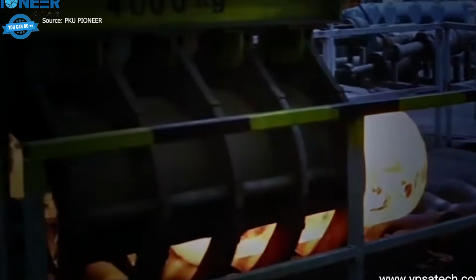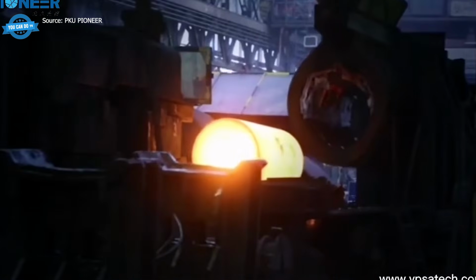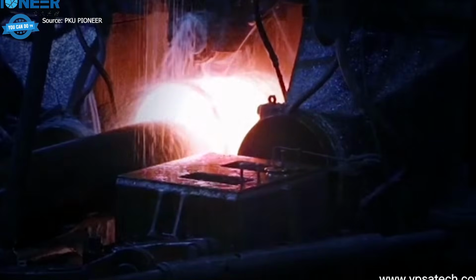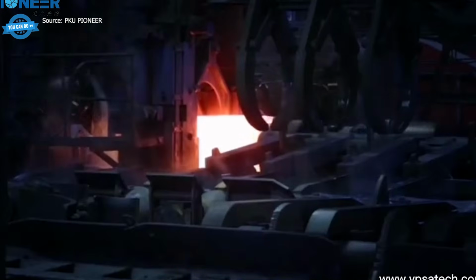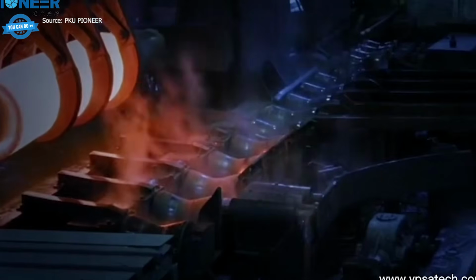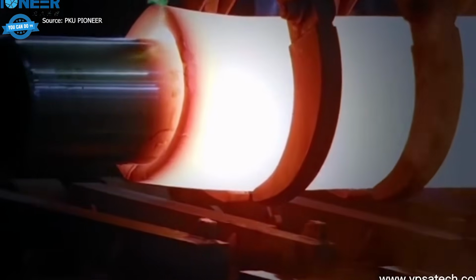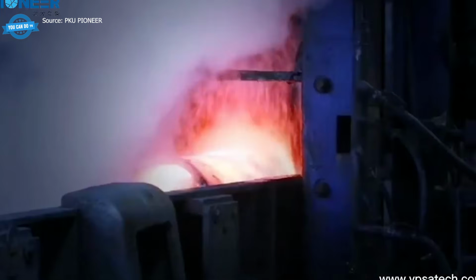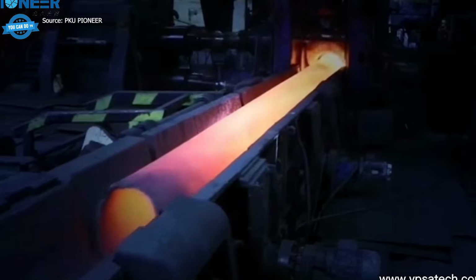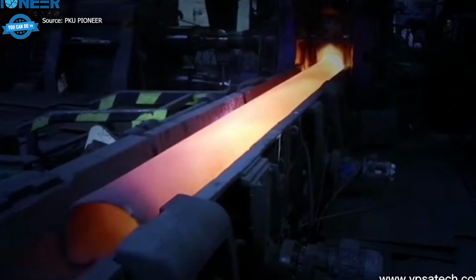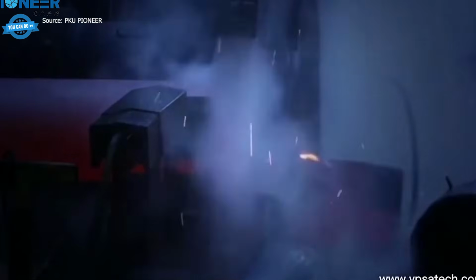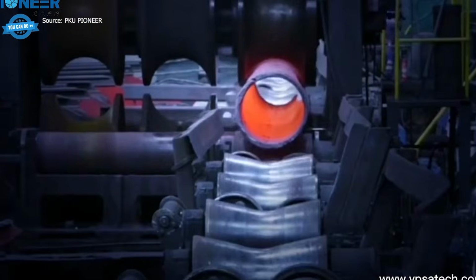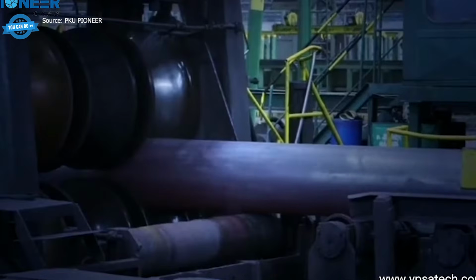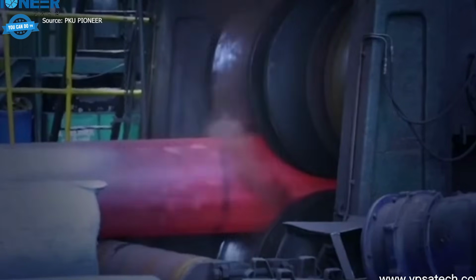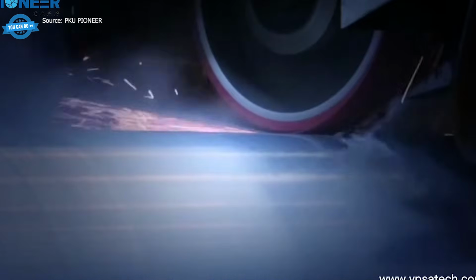For pipelines facing the highest internal pressure, manufacturers often choose seamless pipe instead. A solid round steel billet is heated red hot, then pierced through the center to create a hollow shell. Successive rolling reduces wall thickness and stretches the shell into a long tube. Because there is no longitudinal weld, there is no longitudinal seam that could fail. The trade-off is cost and limited diameter range.